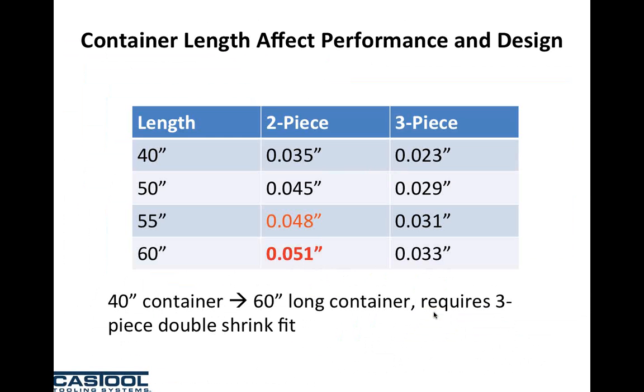This is just a chart that Ken did up for me, and we looked at a 40, 50, 55, and 60-inch container. Two-piece, the 40-inch container will expand about 35 thou, three-piece 23 thou, and again, as dummy block and tooling system manufacturers, we don't worry about 35 thou expansion. We can work with that between the expansion of the dummy block and the flow stress of the alloy.